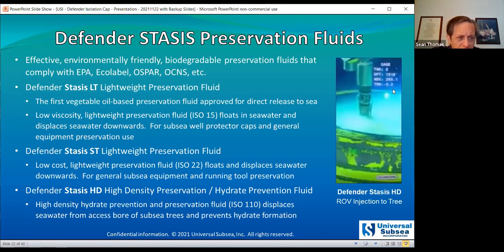So our initial preservation fluid is our Defender Stasis LT. This is the first vegetable oil-based preservation fluid developed for the offshore industry. It's the first oil-based preservation fluid of any type approved for direct release to sea. This is a low viscosity, lightweight fluid. It floats in seawater, it's buoyant in seawater, so if you inject it into a cap or any kind of closed chamber, it will displace the seawater downwards. We also have a lower cost Defender Stasis ST, slightly higher viscosity, and it can be used in this subsea environment and additionally for topsides equipment preservation and running tool preservation. It's also a bio-based product using natural and modified vegetable oils.